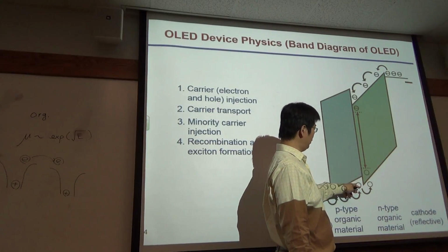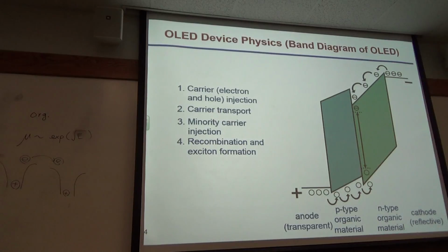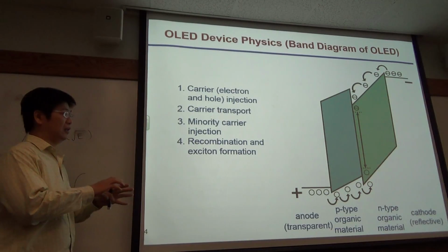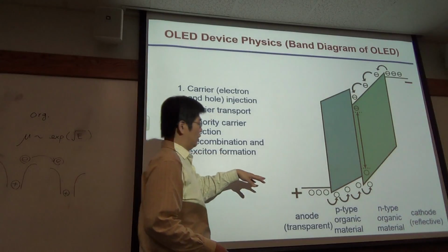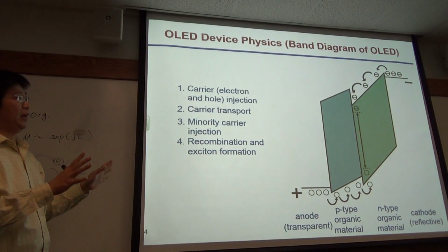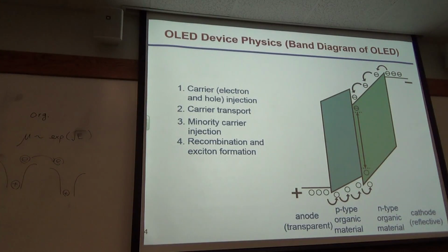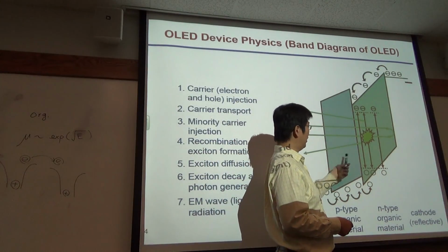Then there are some heterojunctions. For example, they have injection over here, then you can see there's a recombination, because the region is very small, like a quantum dot. So there is a lot of quantum confinement effect, and they will form the exciton. Typically for bulk semiconductor material, excitons are not easy to observe; you have to reduce the temperature. But for the organic material, you have to view the size as like a quantum dot, so they have a very strong quantum confinement effect and form the exciton. Here is a charge carrier for the hole and electron. Once they recombine into the exciton, it becomes neutral, so it will not be affected by the external electric field. It will diffuse for some time, for example nanoseconds, then recombine into a photon. Remember that, again, it is very thin, 100 to 200 nanometers.